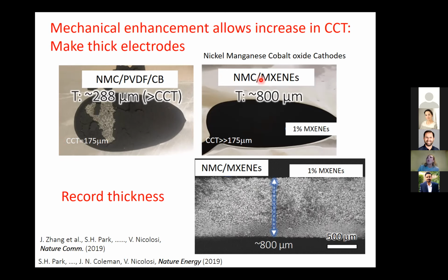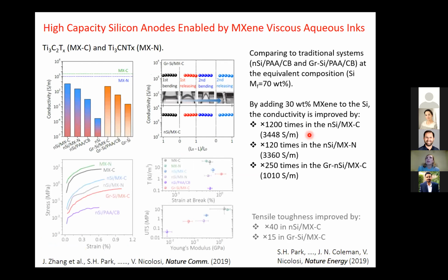In our case, we didn't need to add any polymeric binder. We, of course, use MXenes also as conductive agent. So we basically combined our electrode materials with MXenes, and we could achieve record thickness for our electrodes. And this was unheard of because, of course, the higher the thickness of the electrode material, the higher the performance of the battery. And indeed, we could see that by using MXenes, by adding 30% of MXenes, we could improve the conductivity between 250 times and 1,200 times, depending on which type of silicon we were using.